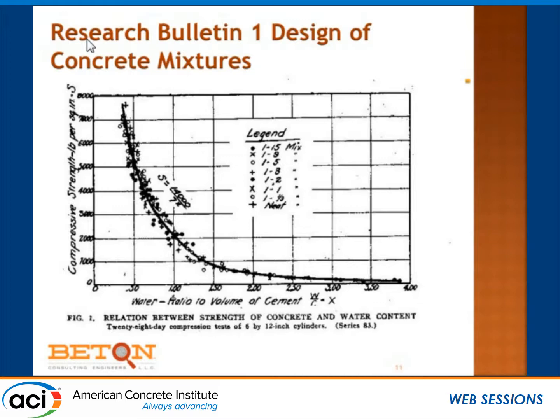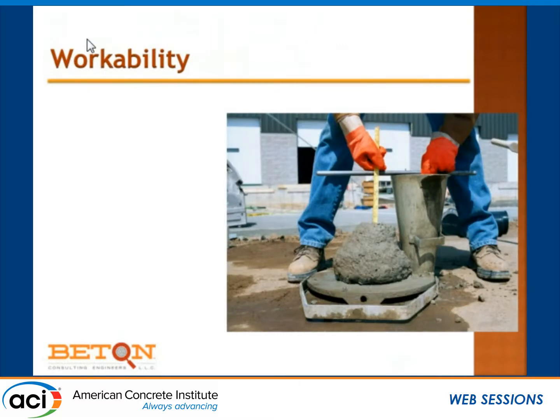And you can see there's a little design curve on there, and you can predict the water ratio. Now, you look at 1.52, because it's the ratio by volume, not by mass. So you have to be a little bit careful, so you have to divide by 3.15. But other than that, it's fine. And so we have this water-cement ratio that is independent. We also, of course, have the Abrams cone. We call it the slump cone now because Abrams, I guess his patent has expired, so anyone can make them.